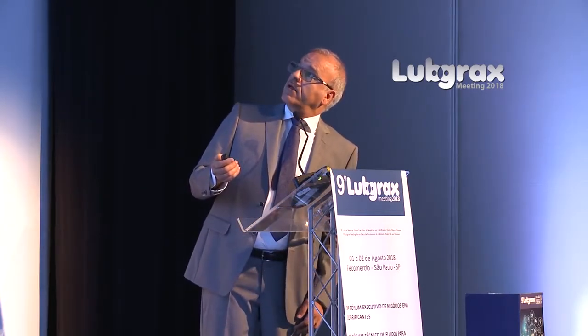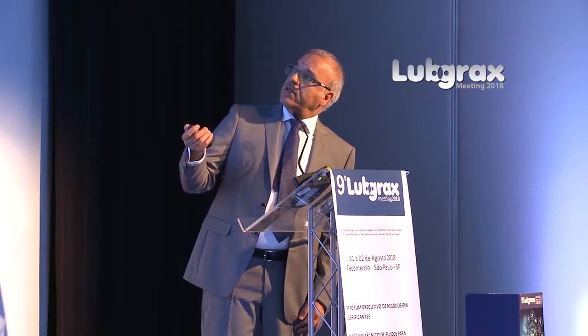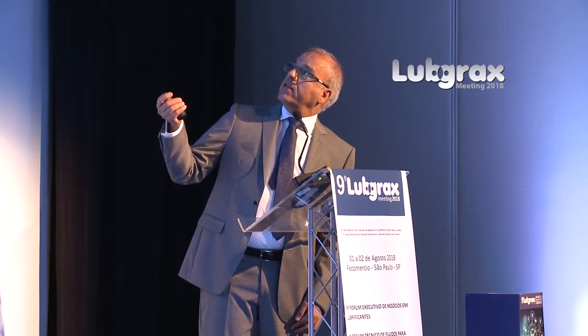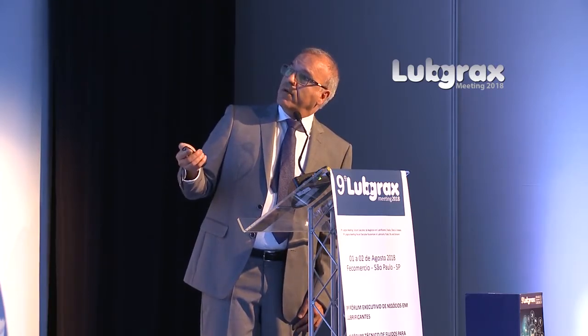We have also done some exercise. For instance, what happens if we blend T600 with, for instance, T110, which is a naphthenic oil with 100 centistokes. Very easy, since they have the same solvency, we can end up with different viscosities. As we increase the viscosity, we lose pour point, but at the same time we gain flash point. But the aniline point, which is indicating the solvency of the product, remained constant.